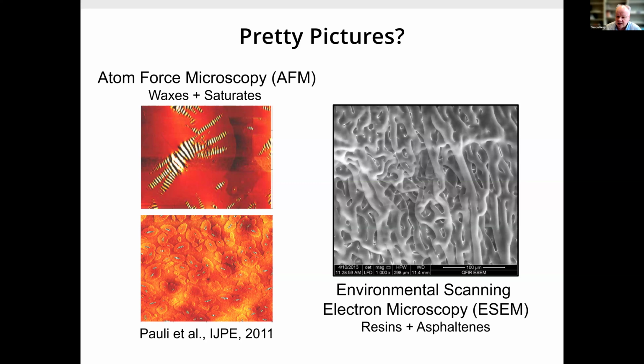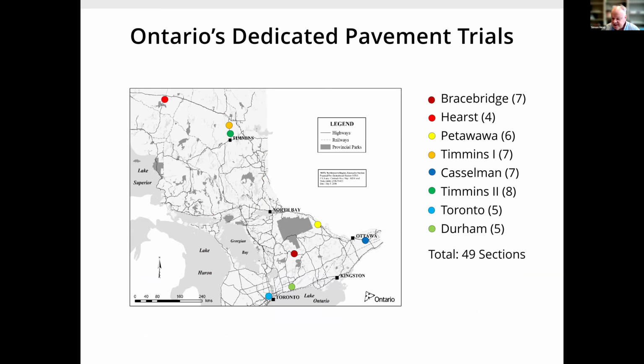If you use a highly oxidized binder from an old pavement and blend it into a new mixture, then this structure will be more pronounced. The volume fraction of asphaltenes will be higher, and you get less stress relaxation. Because it's difficult to do research in the lab, as so many different factors go into road failure, I decided a long time ago to focus my work on looking at pavement trials.